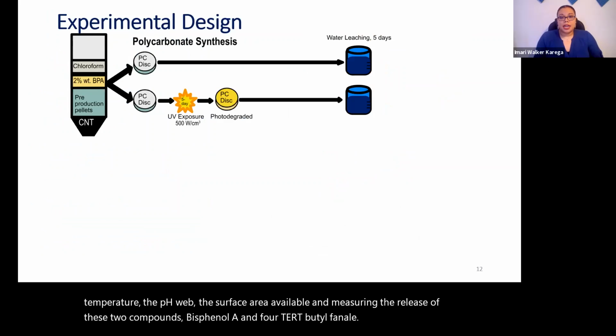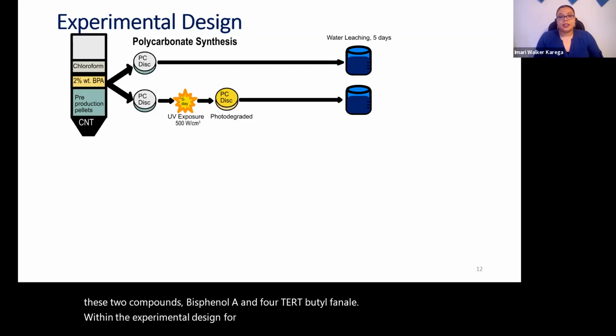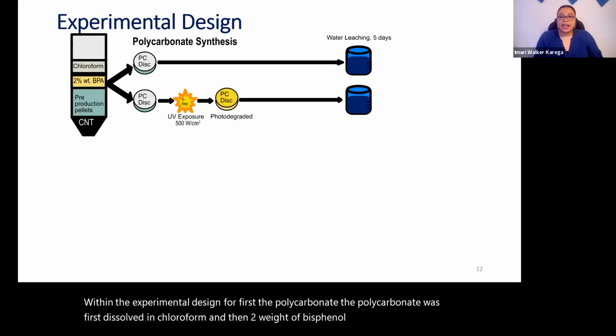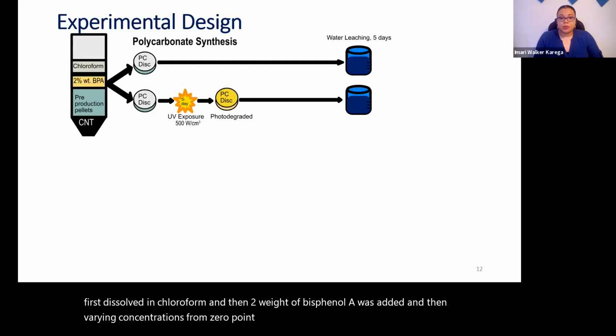In the experimental design, polycarbonate was first dissolved in chloroform, then 2% weight of bisphenol A was added, and varying concentrations from 0 to 0.3% carbon nanotubes were included to make these discs.